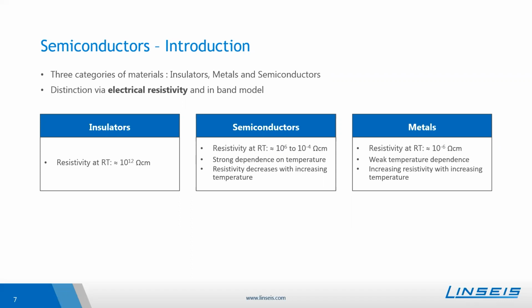Furthermore, the semiconductors and the metals can be distinguished as the resistivity is a temperature-dependent property. For metals, this is only a weak relation, and typically one can see that the resistivity is increasing with increasing temperature. Instead, for semiconductors, there is a very strong dependence on temperature, and the resistivity typically decreases with increasing temperature. So there's also a way to distinguish those two materials. However, one can also distinguish these three classes of materials in the band model.